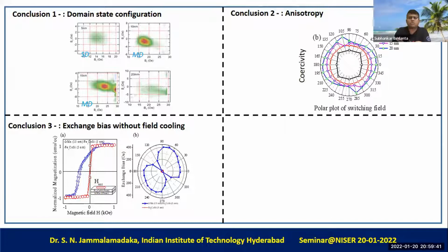I encourage you to look at it through ferromagnetic resonance. That is the best technique. Quantify it, and sure, you probably get more information. But these plots don't indicate anisotropic behavior. Okay, some little anisotropy is there, but it's almost isotropic, you can say.